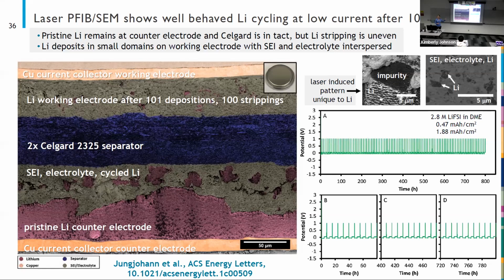And this is the type of thing we're able to get out of the experiments. So this was a coin cell that was cycled 100 times at low current. You can see that we've artificially colored it to make it easier to understand. The top is a copper current collector working electrode shown in peach, and the bottom is the counter electrode. And we have pristine lithium, shown in pink, on the bottom of the electrode. We have excess lithium on the counter electrodes. That's why there's so much lithium left over here.